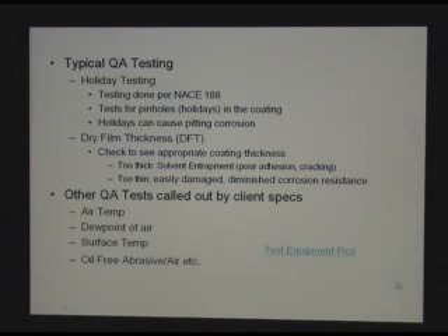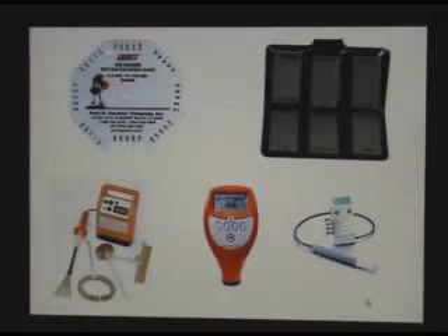Could you please click on the test equipment? Here are some typical tools the inspector uses. There's a wet thickness gauge. This is a set of plates that show how a surface should look once it's prepared to a certain anchor profile. Here is high voltage holiday inspection tools. Here's a brush attachment, or you can have a ring attachment for pipes, or this kind of brush for inside pipes, or a different kind of brush again. This is done up to a voltage of maybe 7,000–8,000 volts to test for imperfections.